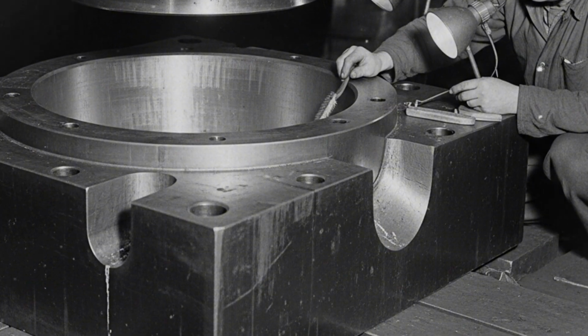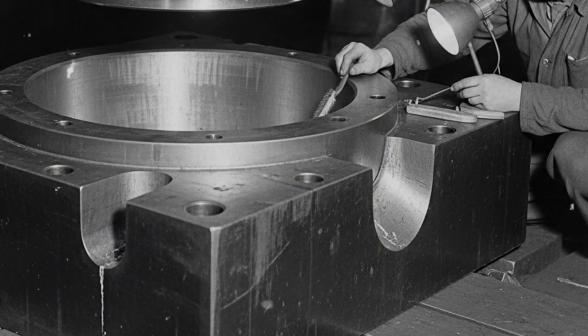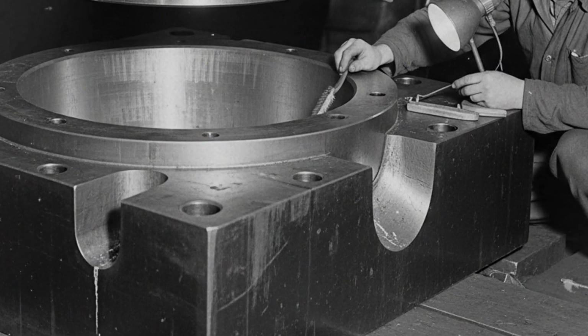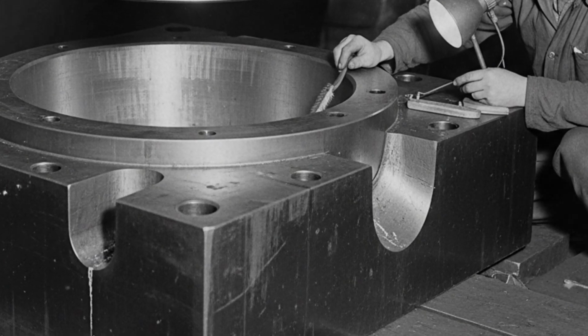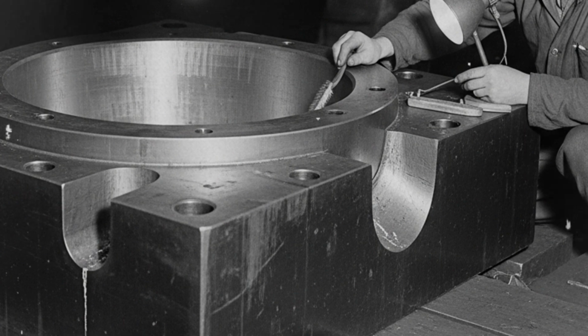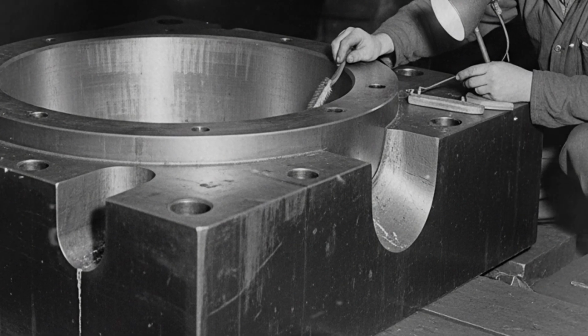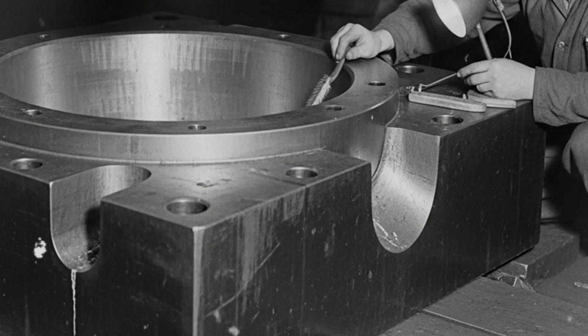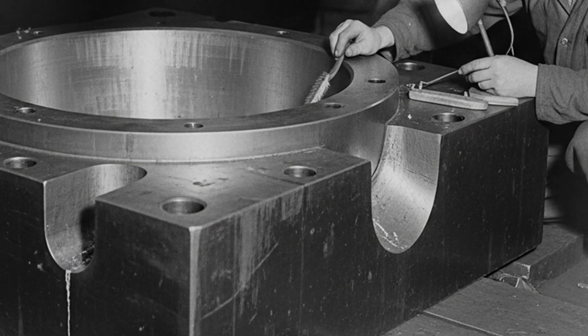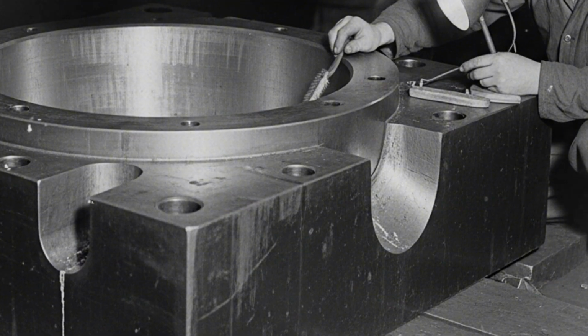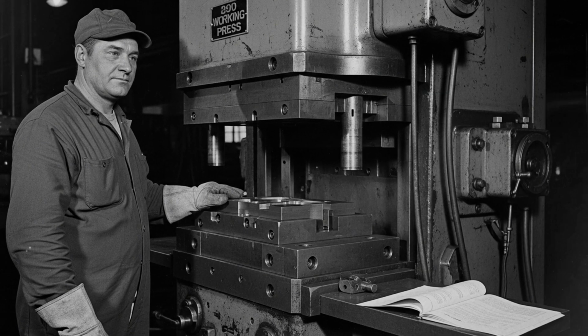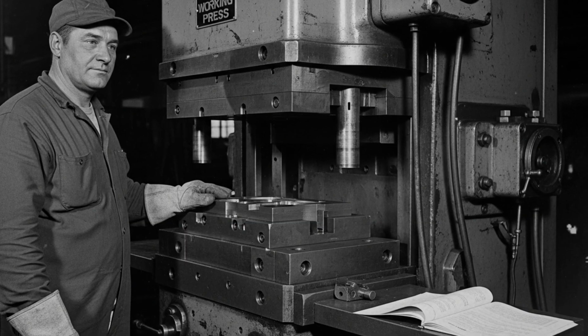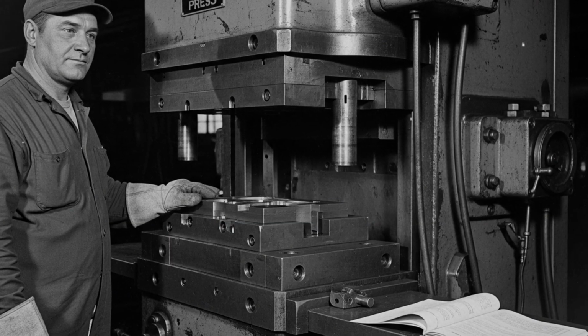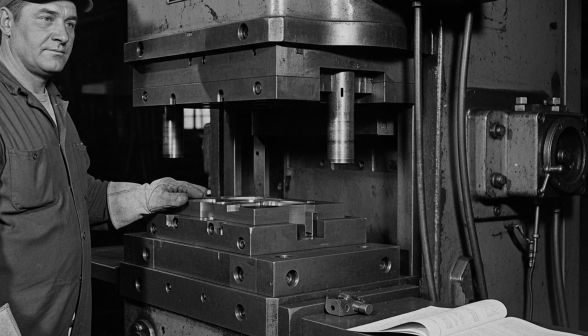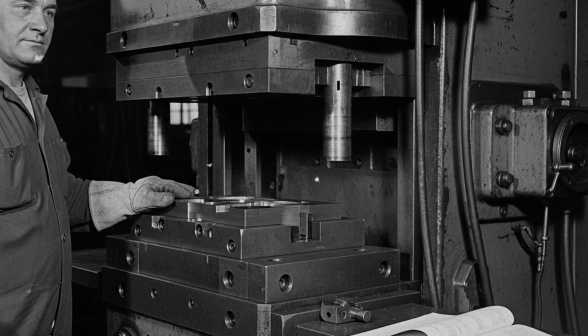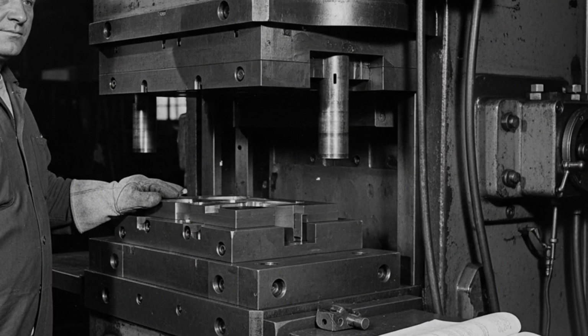Any contamination of the die surface, scale from an improperly cleaned billet, a fragment of lubricant that had carbonized at die temperature, a hairline crack propagating from a thermal stress point, produced a defective forging and, if not caught immediately, risked die failure under the next press cycle. Die failure at full press tonnage was not a gradual event. It was catastrophic and instantaneous. Tool steel fragments under those conditions did not fall. They moved at velocities comparable to low-velocity projectiles.